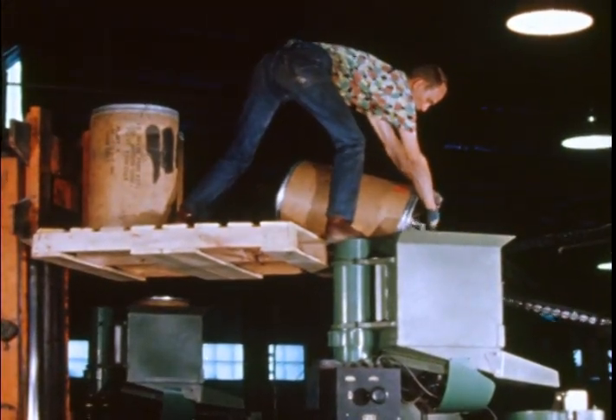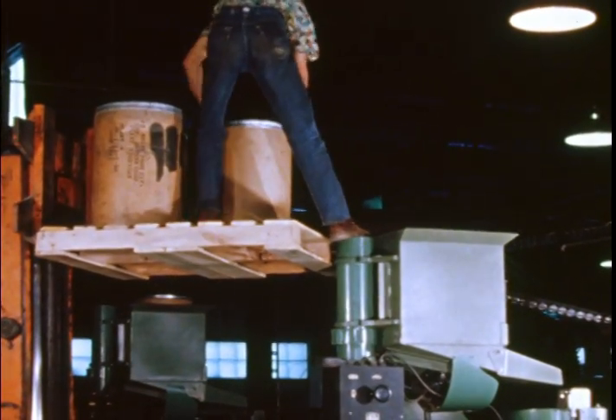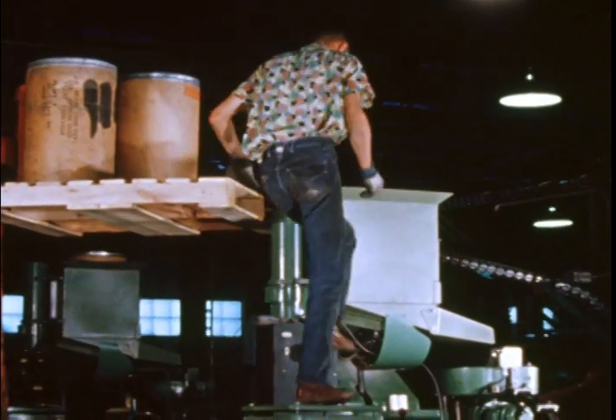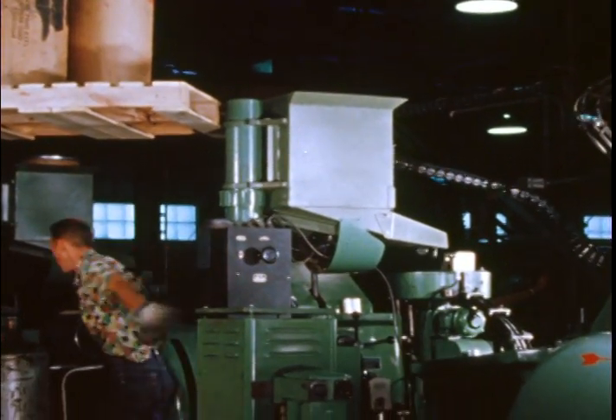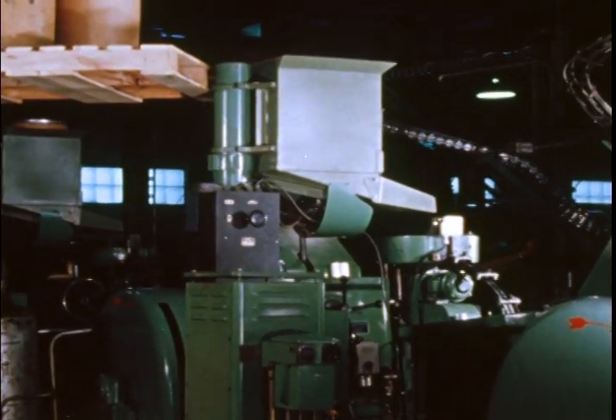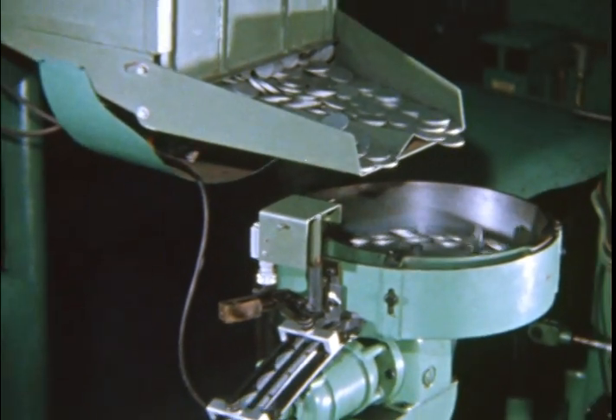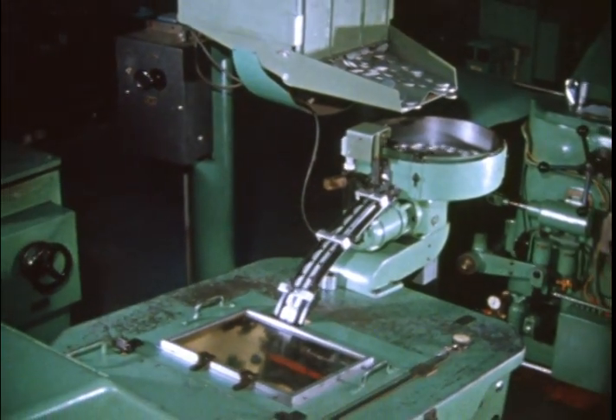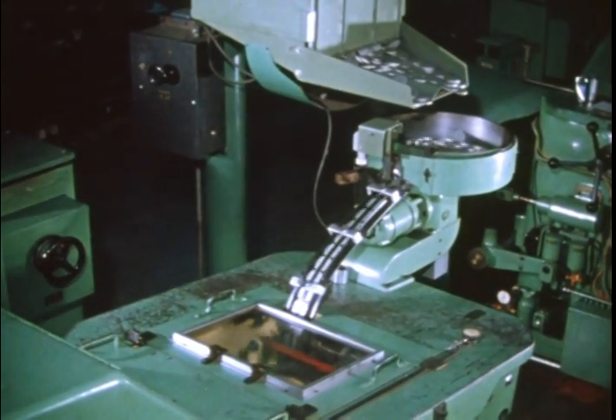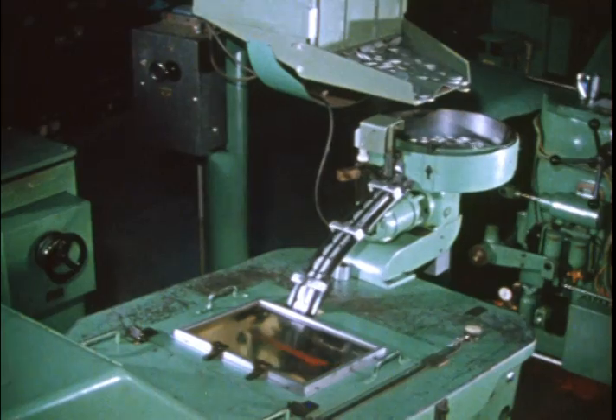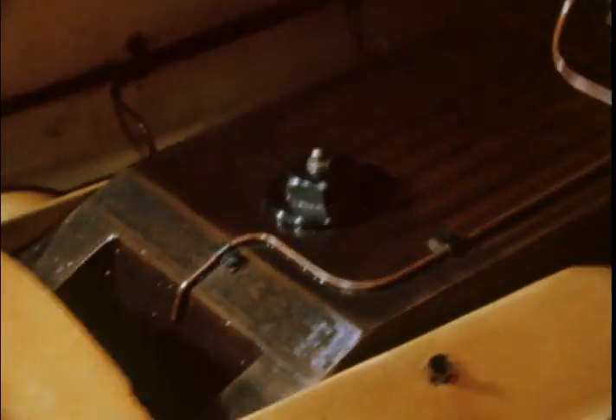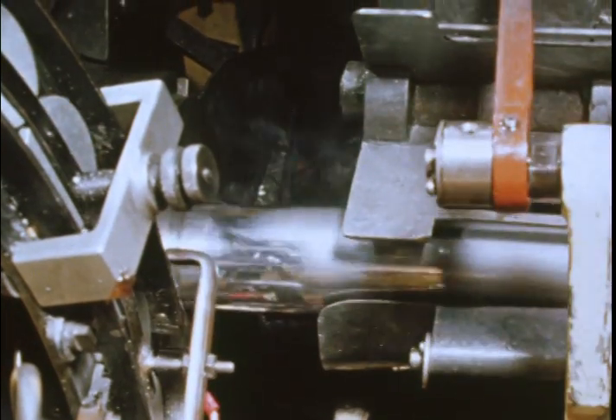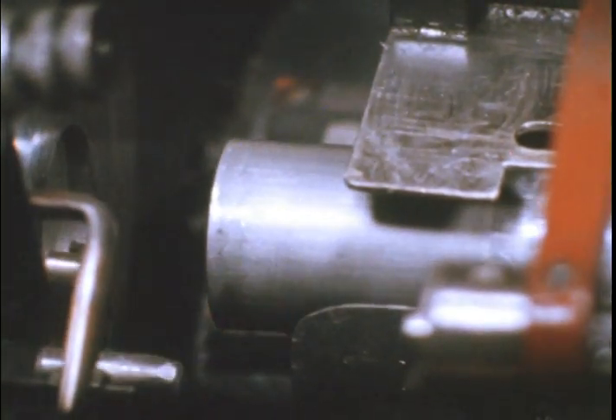Now for the actual can making process. Slugs are dumped into the hoppers above the impact extrusion presses. A feed mechanism brings the slugs down into the press itself, and the can is extruded. Note that the slug is carried into the die cavity and then hit with a punch, the aluminum literally squeezing out alongside of the punch to form the can.